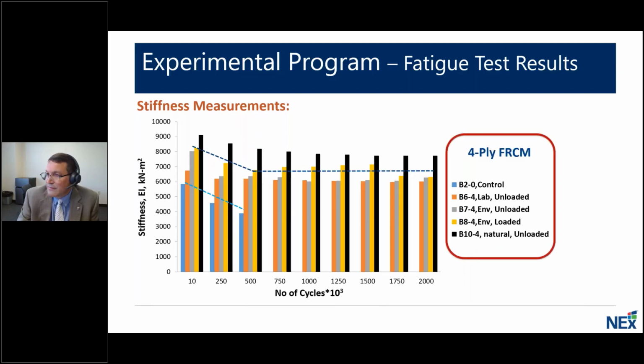For the 4-ply system, we see a similar trend. In this case, the loading is, of course, higher because the reinforcement added to strengthen the beam utilizes 4 plies, and at that higher load level, the beam without any strengthening, in blue, you can note that one actually failed during the fatigue cycles past 1,500,000 cycles. Only the control specimen without the strengthening system failed due to the fatigue testing, and all the remaining strengthened specimens all survived 2 million cycles.